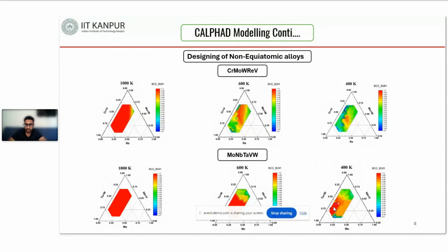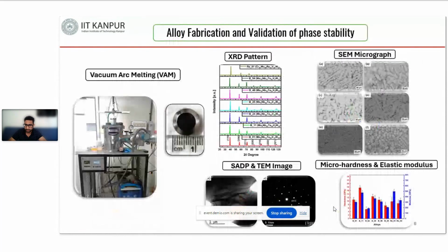So once we got this result from CALPHAD, we wanted to validate it with an experimental technique. We used vacuum arc melting to prepare these alloys and did XRD testing. We did XRD testing on more than six or seven alloys, and we found that all of them show a single phase structure.